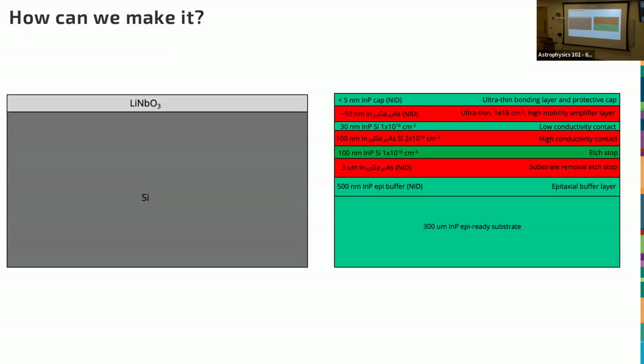Indium phosphide is just there because that's a good substrate for it. You can actually just grow MOCVD on indium phosphide. It's also important that I can grow these with good chemical orthogonality. So I can use different acid chemistries to only etch indium phosphide and not indium gallium arsenide and vice versa. And that is going to allow me to do the following.